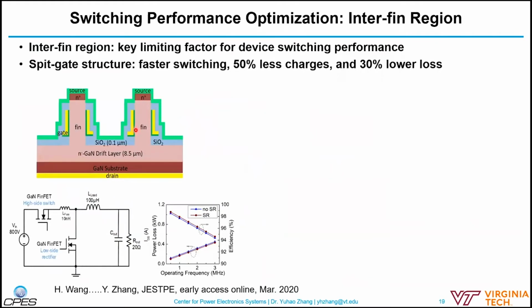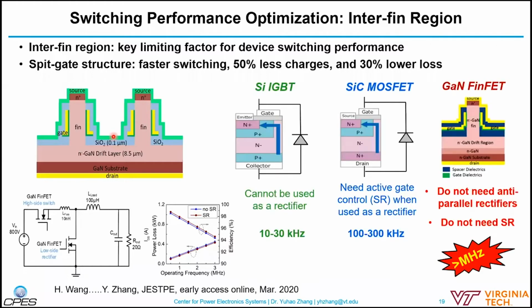And also, if we think about switching performance, like capacitance and charges, the charges are particularly interesting in these devices because they are related to the interfin designs. For example, when we switch devices, we need to supply or extract the depletion charges in the drift region. If we can remove the gate in the interfin region, then we can supply the charge using the source to drain current instead of the gate current, and as such the switching speed can be much faster. So here is a comparison between the silicon IGBT, which is a dominant medium voltage device today, the silicon carbide MOSFET, and the GaN FinFET.